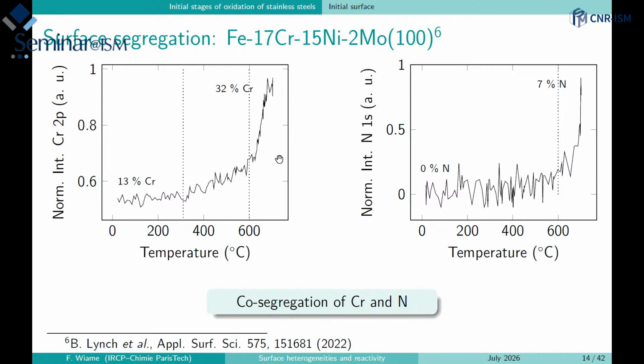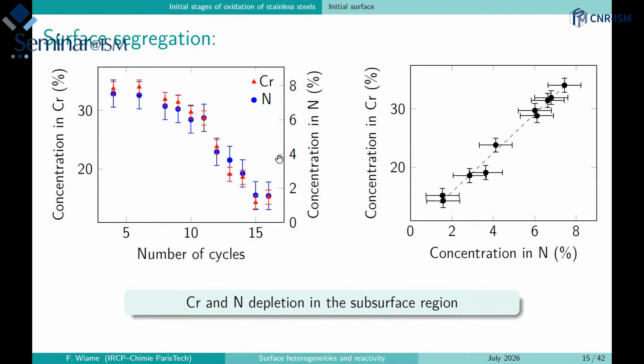So the first heterogeneity is, as I said, related to chemistry, but in fact the composition of the surface is even more complicated than this, because if we repeat a cycle of sputtering and annealing, then we will have a change in the composition. And so it will also depend on the history of the preparation of your surface. So in fact, you will almost never have 2 times the same composition and the same structure of the surface. So it's really complicated to say that we have one composition.